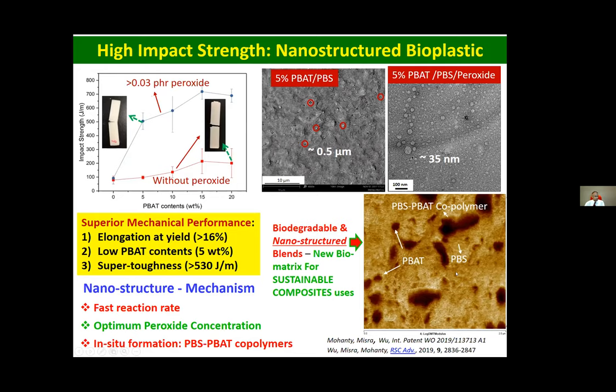So only a small amount of PBAT. If you use a lot of PBAT, yes, you can increase the toughness, but you cannot get enough stiffness. PBS gives enough stiffness. But once the PBAT is distributed in nanoscopic size in your PBS matrix, then you get a stiffness-toughness balance. So surprisingly, we got various mechanical property improvements. Without that additive, our elongation is very low. But with the additive, you can see how the elongation has gone up to 700%. So that's the beauty of this nanostructure, and that nanostructure could happen by a peroxide chemistry that we did.